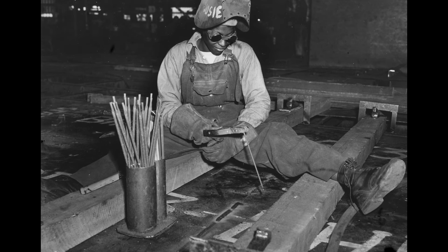The Liberty ships were victims of what metallurgists call brittle fracture propagation. The steel used in their hulls, a carbon-based shipbuilding grade, behaved well in warm waters, but underwent a critical shift in near-freezing Atlantic temperatures. Below roughly 40 degrees, the metal's ductility collapsed. Normally, steel absorbs stress by flexing slightly, bending instead of snapping. But cold robbed it of that flexibility, making it behave more like glass than the tough alloy welders handled under California's mild skies.